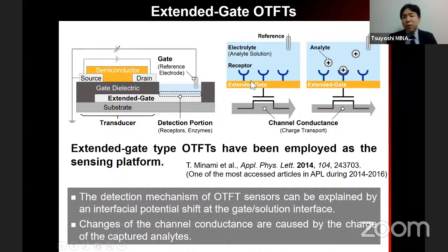In that case, we employ the self-assembled monolayer for the fabrication of the receptor, so the receptor can be fixed on the extended gate. If the target analyte, a plus or minus charged molecule, is bound on the surface of the extended gate electrode through molecular interactions, we can see changes of the surface potential of the extended gate electrode.